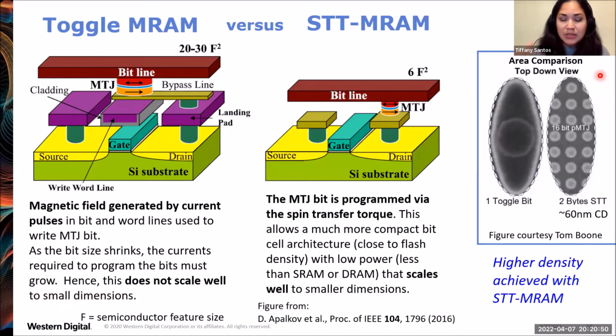This type of writing scheme does scale well to small dimensions, and you can see that easily here in this comparison in this top-down SEM image, comparing the area occupied by 16 perpendicular magnetic tunnel junction bits. These have about a 60 nanometer diameter. And these fit into the area of just one Toggle MRAM bit. And so it's easy to see here that it's spin transfer torque MRAM that will move us forward to a more high density memory.